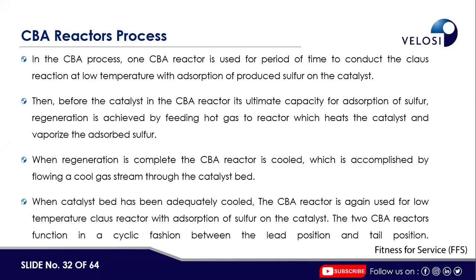CBA reactor process. In the CBA process, one CBA reactor is used for a period of time, let's say 24 hours, to conduct the Claus reaction at low temperature with adsorption of produced sulfur on the catalyst. Then, before the catalyst in the CBA reactor is fully adsorbed, the level is increased and its equilibrium level is reached. Then regeneration of the same catalyst is required by feeding hot gas to the reactor, which heats the catalyst and vaporizes the adsorbed sulfur. When regeneration is complete, the CBA reactor is cooled by flowing a cool gas stream through the catalyst bed.